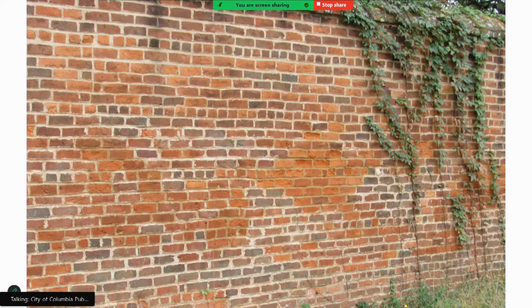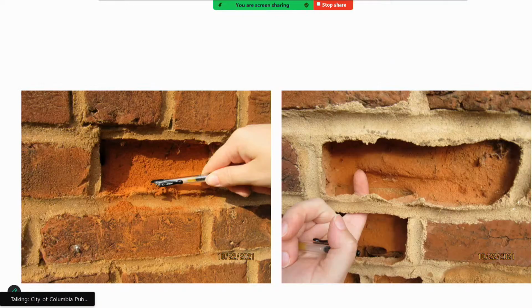It's when the outer tough coat that's been fired of the brick crumbles away, and then inside the wall, it just turns into dust. So you can see there, when you see a wall where you just have the mortar outline of where the brick is supposed to go, that's pretty good indication that that mortar is too hard for that brick, because it's the last thing that's standing and the brick is all gone.